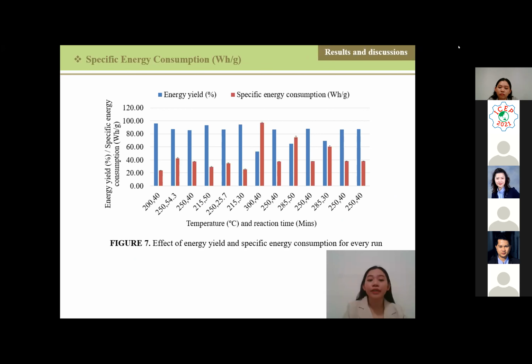As shown in figure 7, high temperature and longer reaction time resulted in high energy consumption. This gave high specific energy consumption, which is not recommended, even though the high heating value and energy densification ratio were high. It's worth noting that not only high heating value, but also mass yield must be considered for torrefaction optimization.